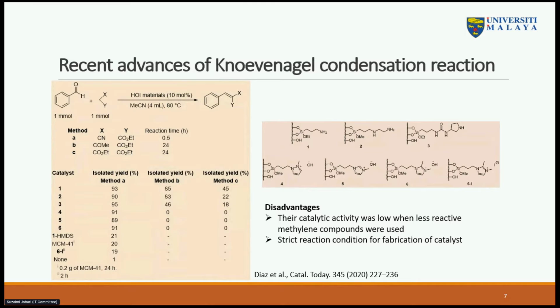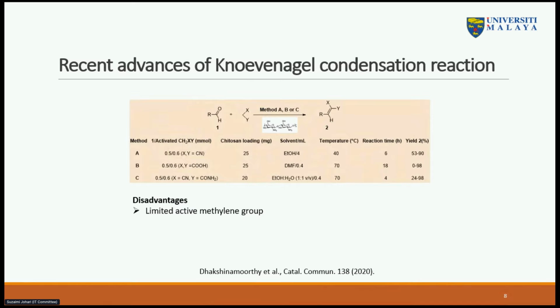Yeah, the same trend also can be seen in this work, where the catalytic activity was low when the less reactive methylene compounds are used, and also a very strict reaction condition for the preparation of the catalyst. And also this recent work has been done by Dhakshinamoorthy in 2020. This work uses a bio-based type of catalyst, also containing a very high nitrogen content in the catalyst. However, there is still the limitation of the active methylene compound used in this reaction, and also the variety of the substrate group gave quite not very high yield.